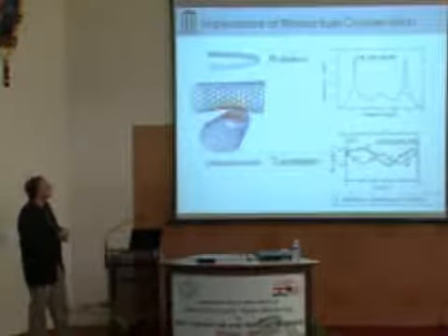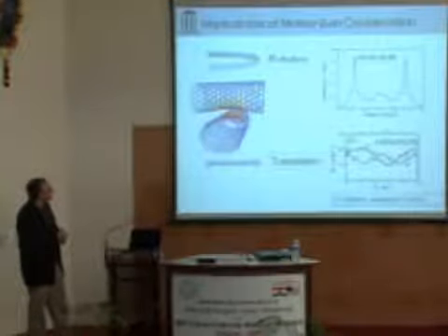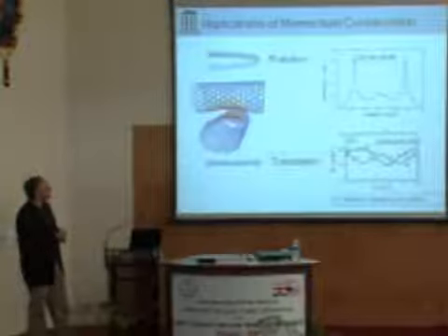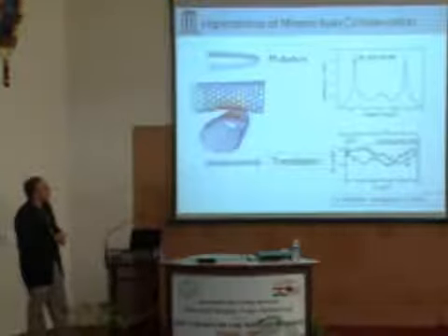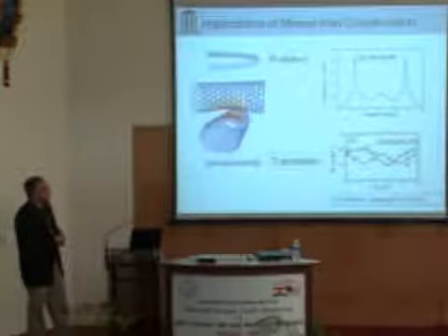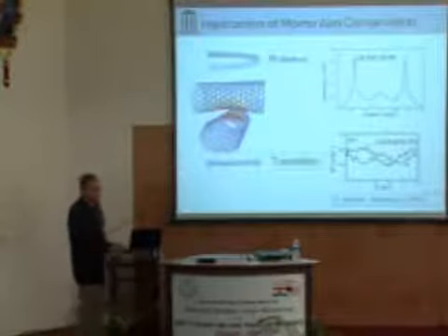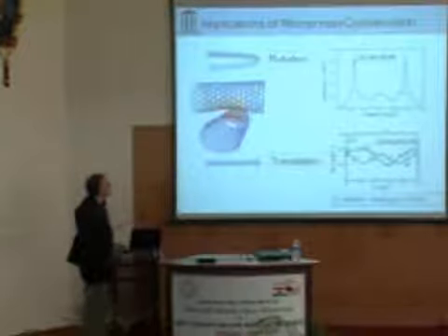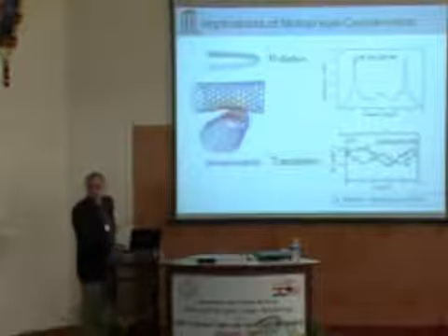You could rotate it. You twist this nanotube with respect to this one, or you can translate. You can move this nanotube rigidly with respect to this one. In either case, you see changes in the resistance of the contact according to either the rotation or the translation. And again, these changes here correspond to atomic lattice interlocking effects, similar to what we see in the rolling and the electrical contact. So the challenge for us was to say, can we put these effects into a device?